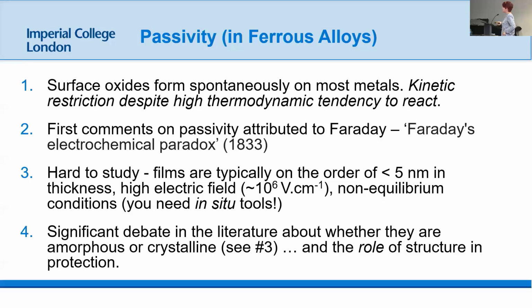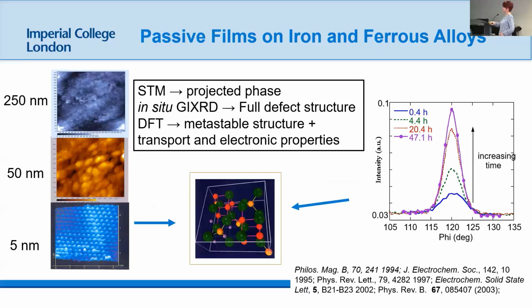So what we did was say, well, can we use STM to answer this riddle? And it turns out if you've got the right technique, then absolutely you can. Look, here's the passive film. It's beautifully crystalline. Nobody's going to argue with that. More interestingly, or equally interesting, at this length scale you can clearly see the atomic resolution, and this is consistent with a spinel oxide 111 projection. As you zoom out from that, you start to see that it's made up of these little crystallites. So this crystalline oxide is actually nanocrystalline. And then on top of this, you can see for our material, these are the grain boundaries in the bulk metal.